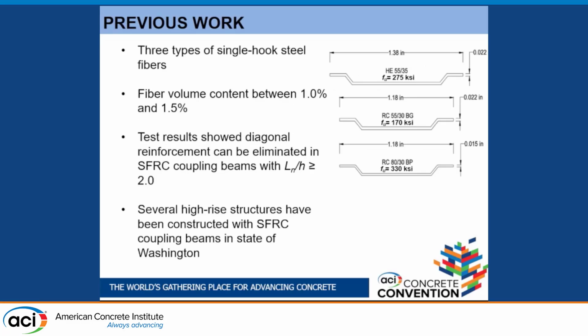We have shown in the past that that is possible in some cases. We had evaluated 3 types of steel fibers, all hooked, but we call them single hook because it's just a single hook at the ends. We evaluated these fibers in volume fractions between 1 and 1.5%, so all the way to about 130 to 200 pounds per cubic yard. We've seen that in some cases we can eliminate diagonal reinforcement if we're dealing with aspect ratios, span to depth ratios, of at least 2.